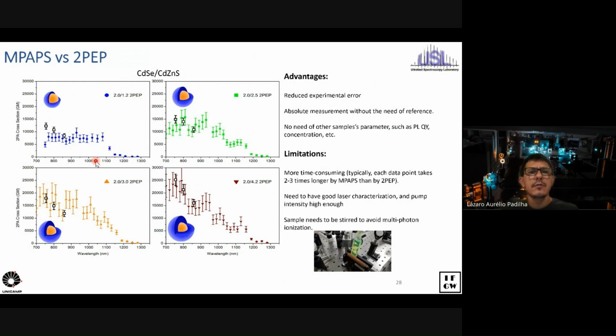So we did this for the core shell and compared the 2 different techniques. This one that we just introduced, the MPAPS, and the 2-photon excited photoluminescence, we see pretty good agreement. Of course, no technique is perfect, right? So this technique we just proposed, the MPAPS, is pretty good because it reduces the experimental error. It gives you absolute numbers without needing a reference. And you don't need other sample parameters like PLQY or concentration. So it specifically reduces your relative error when you want to compare different samples.